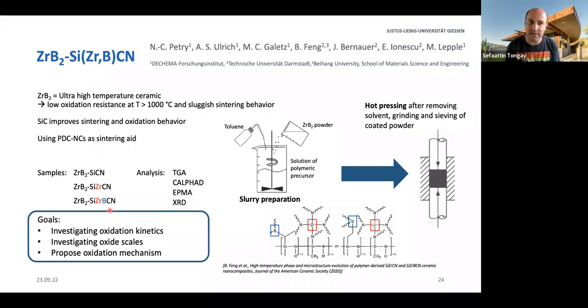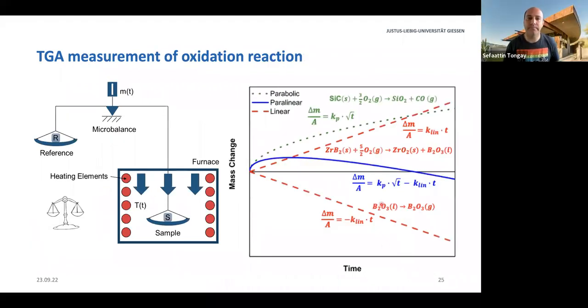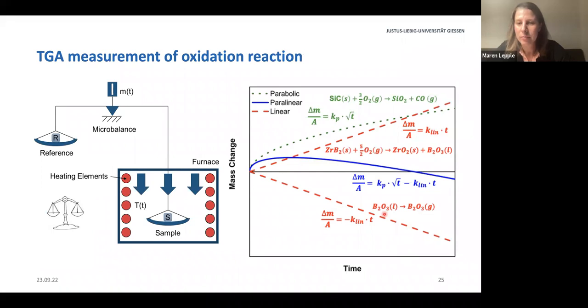Which element is missing during the reaction? Can you remind me that, if possible? Boron is missing. For example, the boron, the liquid, will evaporate at these temperatures. Okay, and what was the temperature roughly? 1300 degrees centigrade. 1300. Okay, very good.